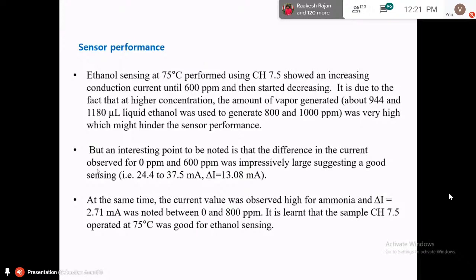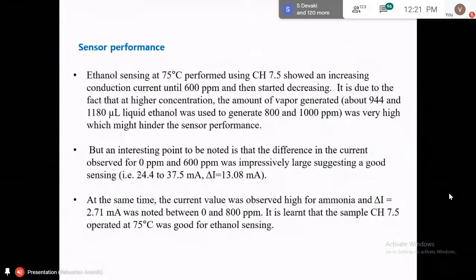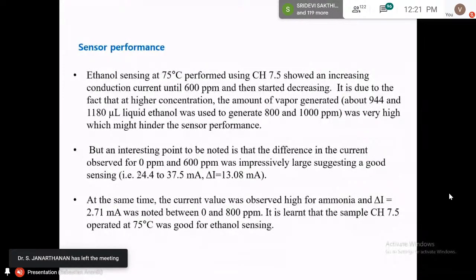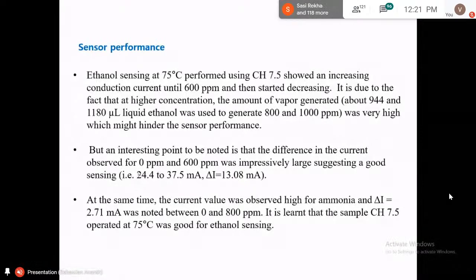But an interesting point to be noted is that the difference in the current observed from 0 to 600 ppm was impressively large, which suggests good sensing. At the same time, the difference for ammonia is only 2.71 mA. That is small. So it is learned that CH 7.5 operated at 75 degree was good for ethanol sensing. So ultimately what we found was that our cyclohexane coating, coated for 7.5 minutes in the PECVD, is very good for ethanol sensing until 600 ppm.